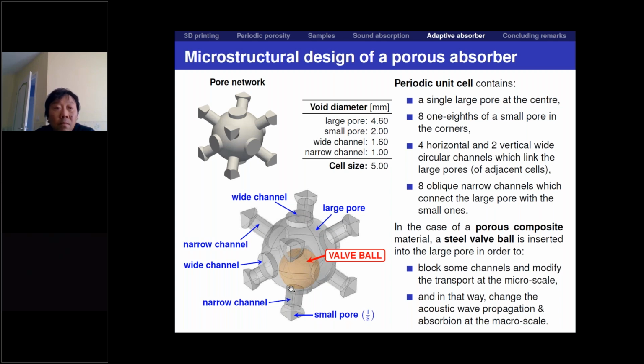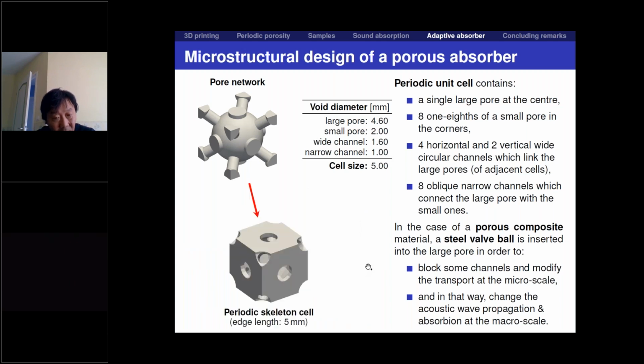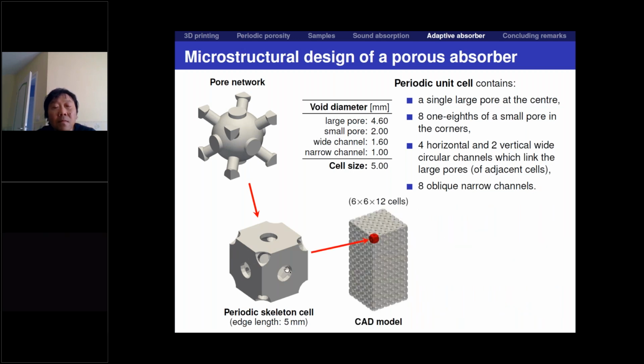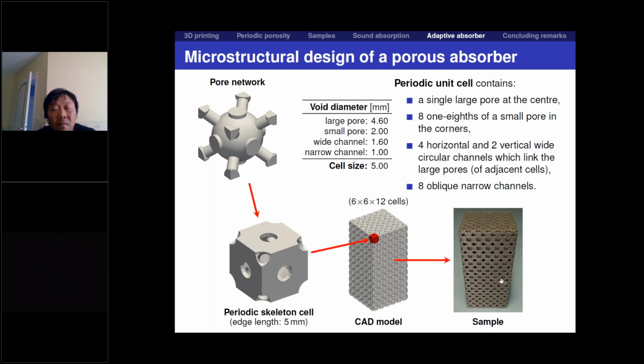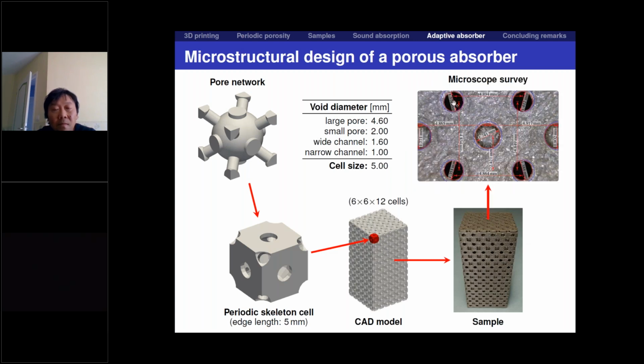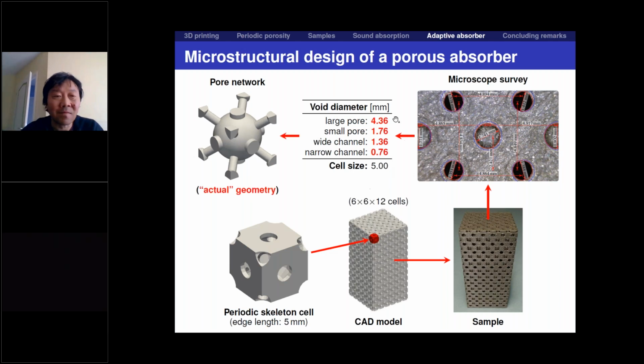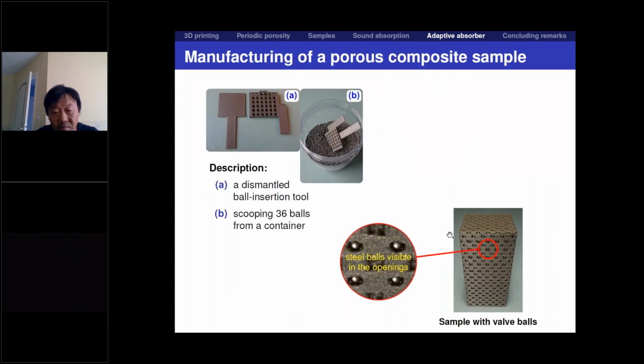And these valve balls simply block some channels, so they change some parameters like viscous tortuosity, viscous characteristic length, inertial tortuosity, and in that way we may expect to have different absorption depending on the position of the valve balls inside the cells. So this is the periodic skeleton. For one cell we have an array of these cells, and we have such a sample, and you know that we always need to examine our sample under the microscope in order to update the geometry that we use for calculations to the actual geometry. This is maybe the main slide from the point of view of the manufacturing.